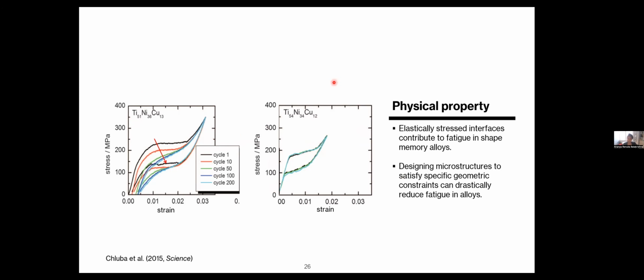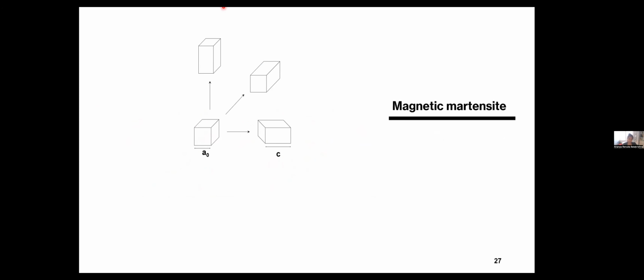But now the question is, can we do a similar thing in the case of magnetic materials? In the case of a shape memory alloy, the material undergoes a phase transformation from a cubic to a low symmetry phase. But in magnets, this phase transformation from the paramagnetic to the ferromagnetic phase is also accompanied by the presence of a spontaneous magnetic dipole. And this dipole can have 2 different crystallographic orientations. In this case, you can have 6 different tetragonal variants with magnetization along the opposite direction.